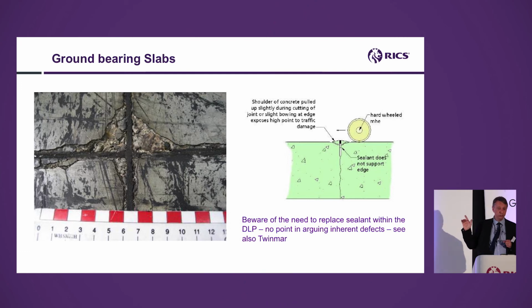And what we're looking at here is the sawn contraction joints in the floor. You know what this is all about. If you've got to control shrinkage, so you want cracking to occur where you want it. So before the concrete is fully set, you cut in a 5mm joint, 50mm through the depth of the slab, with the hope that when you get the shrinkage, it will crack there and nowhere else. That's fine. The trouble is that concrete does shrink, and it particularly shrinks during its first few months of life. So the filler that you put in that joint needs to be able to accommodate shrinkage. And that shrinkage is going to be greater during the first few months of life than it is after the first few months of life.